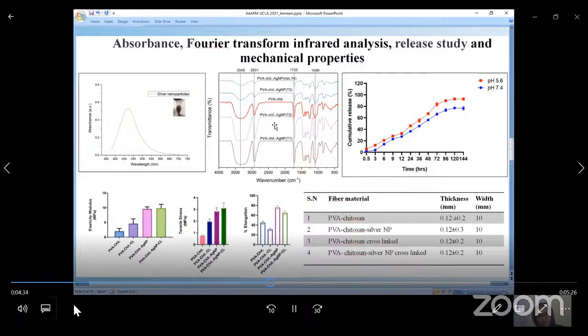FTIR was carried out on the fibrous sheet which we obtained, wherein the control was kept as PVA and chitosan, that is the plain without Ag nanoparticles, and the rest of the 4 spectra are those with the AgNP. Herein the saturation was obtained when the thickness of the fibers increased, and the amide bonds were flattened a bit when AgNP was incorporated, showing that Ag and N bonds were formed. Then, in order to study the release pattern of AgNPs, we did the analysis in PBS, the phosphate buffer, at pH 5.6 and 7.4, showing that at 5.6, that is the acidic pH, more release of AgNPs was observed. The estimation of AgNPs was done by ICP-AES throughout the study.